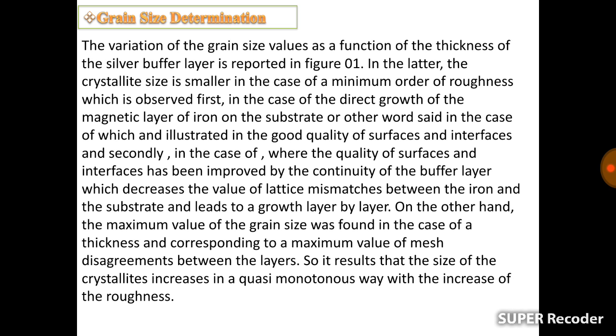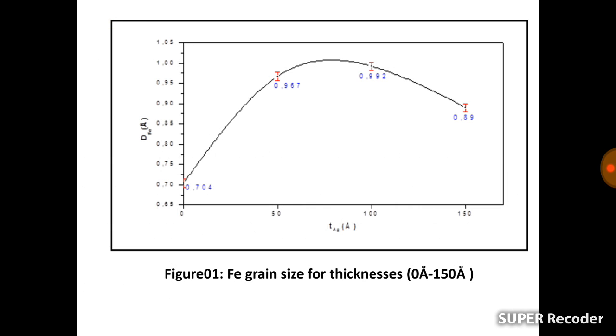Grain size determination. The grain size values as a function of the thickness of the silver buffer layer are reported in figure 1. In this figure, the crystal size is smaller in the case of the minimum order of roughness, which is observed first in the case of the direct growth of the magnetic iron layer on the substrate, illustrating the good quality of surface and interfaces, and secondly in the case where the quality of surfaces has been improved by the continuity of the buffer layer, which decreases the lattice mismatch between the iron and the substrate and leads to layer by layer growth.